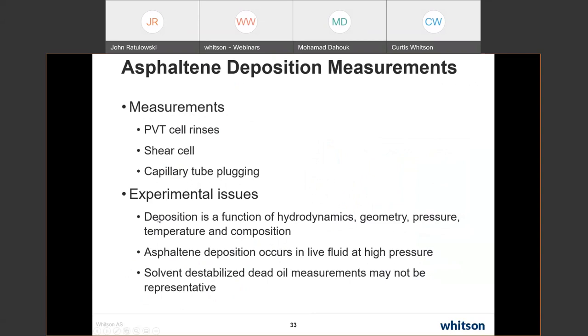I mean, deposition is a function of hydrodynamics, geometry, pressure, temperature, and composition, of course, just like with wax. Asphaltene deposition occurs in live fluids at high pressure. So we can't really do this often in our laboratory experimental conditions. So we resort a lot to solvent destabilized dead oil measurements. I say they may not be representative, but I think there's been a lot of work done over the years that shows where we can use these measurements effectively.